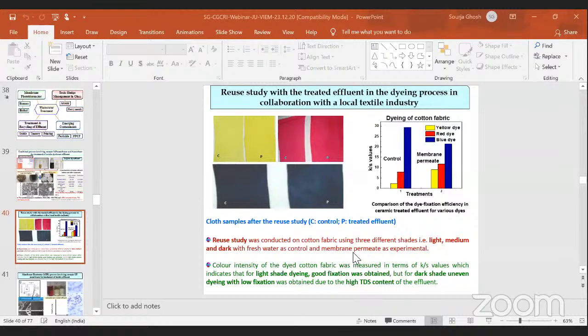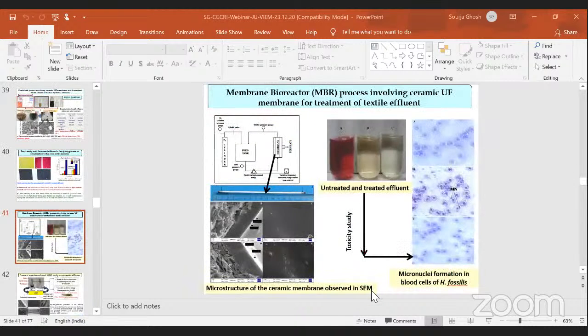And you can see that light, medium and dark shade dyeing was done with fresh water as control and membrane permeate as experimental. The color intensity of the dyed cotton fabric was measured in terms of K/S values, which showed that the process was effective for the light shade dyeing, wherein good fixation was obtained with that membrane treated water. But as we go for the dark shade dyeing, low fixation was observed due to the high TDS content of the effluent.